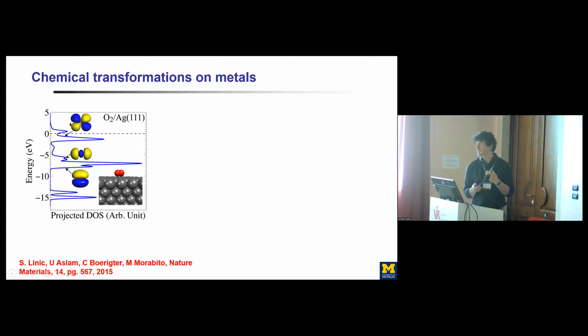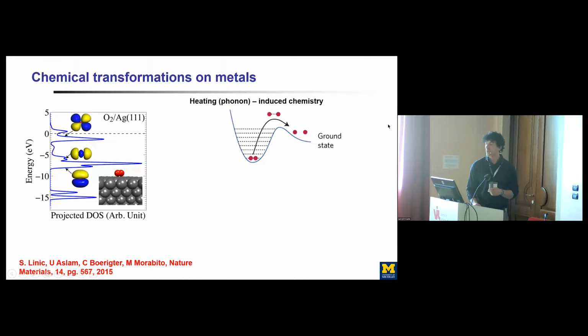So if you want to activate this in a thermal process, you would heat this nanoparticle. Your phonon mode of the nanoparticle would couple with the vibrational mode of this oxygen. You start stretching this oxygen-oxygen bond. This anti-bonding state would sink below the Fermi level. You would populate that anti-bonding state. You would go over something that's called transition state, and you would dissociate this oxygen and form atomic oxygen.